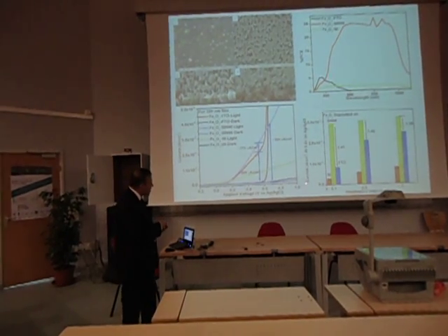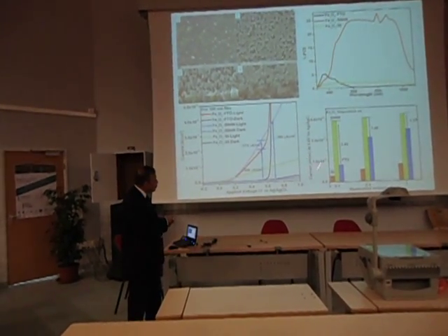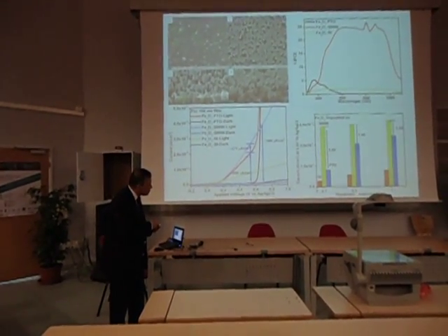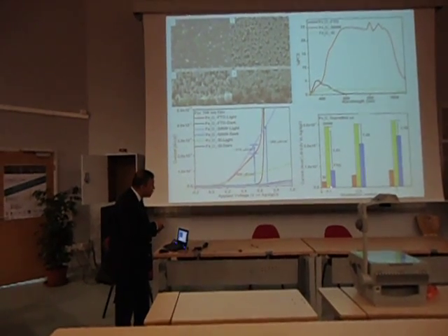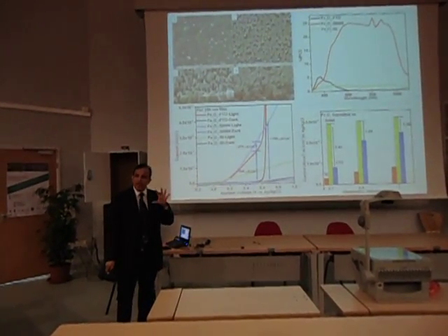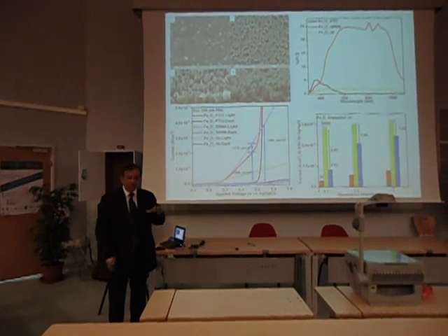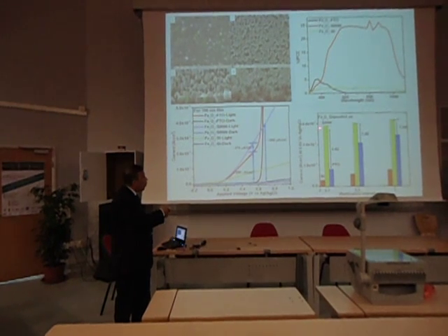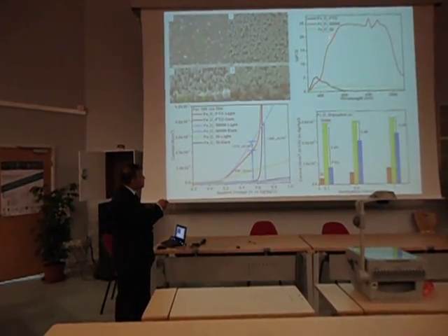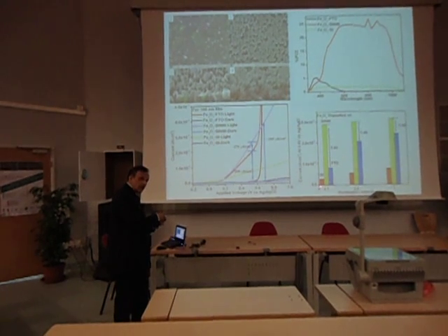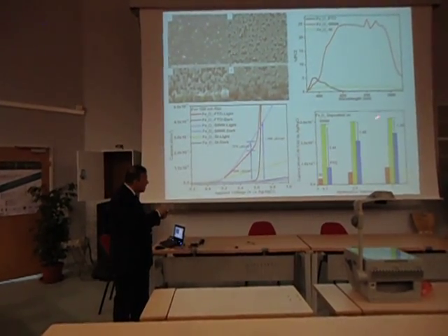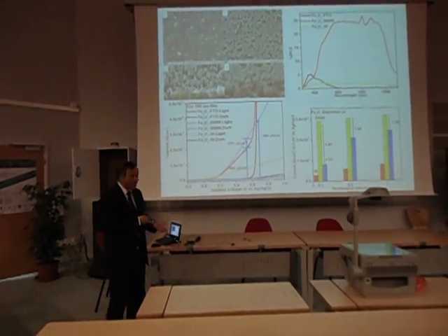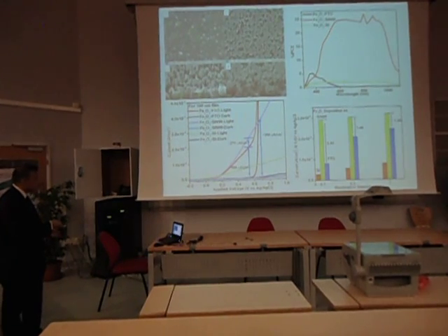And you will see here that this is a photoelectrochemical response. When you consider the nanowire case, this is 1 sun intensity. This is 0.5 sun intensity. This is 0.1 sun intensity, which is very weak, like an evening sun. What you find here is that the response is not decreasing that much. But if you were to only use Fe2O3 or Fe2O3 on silicon, you look at the dramatic decrease in this particular response. So we have here almost a low light category of trying to develop this particular application and so on. So a number of interesting things can be done in this situation.